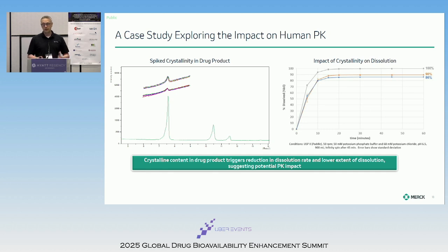But in this particular instance, at Merck, we had a product where we were seeing low levels of crystalline content in the drug product. There was concern around the risk that carried. There was concern around the ability to control that. And when we saw low levels of crystalline content, we also saw a corresponding reduction in the dissolution rate, suggestive of a potential impact here to PK performance. And so we actually went ahead and decided to execute a deliberate clinical study to interrogate this further.